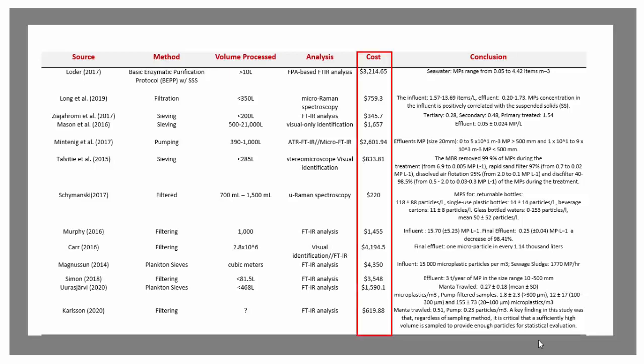In particular, consider the cost of these different analytical methods. They range in price wildly from $220 a sample to over $4,000 for a sample. This is due to the amount of time required to prepare the sample for analysis, and also the length of time for analysis on the equipment. If you're using traditional micro FTIR or micro Raman using a rastering type stage, your analysis times could be multiple days. If you're using a focal plane array detector, your analysis times can easily be 24 hours or greater.